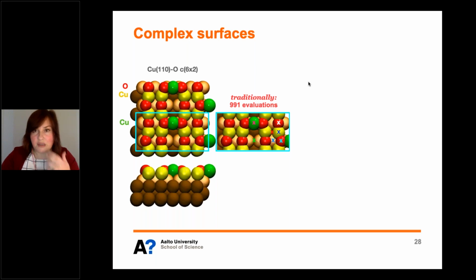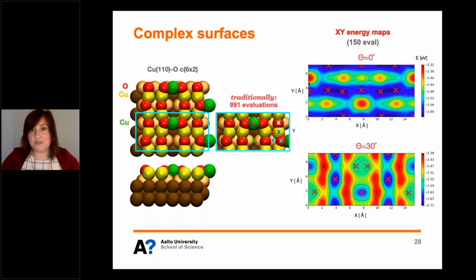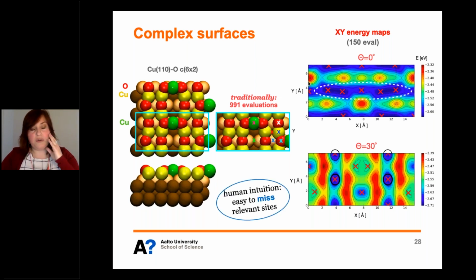And then we plugged this into BOSS, and it took us a little longer to converge, but we found these kinds of energy maps, which are incredibly complicated, with lots of different minima. And it's also showing minima in the sites where Diego didn't think to look. And this is a problem for most of our experimental collaborations. They work with lots of complex oxide surfaces where the lattice sites are not always well defined. So with human intuition, it's really easy to miss the relevant sites. It's much better to get the AI to take care of all of this for us.